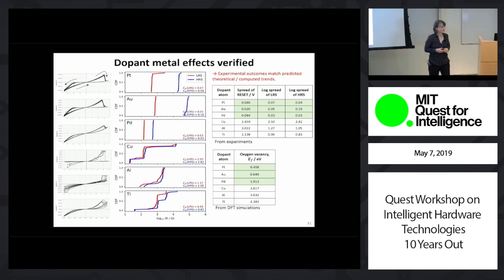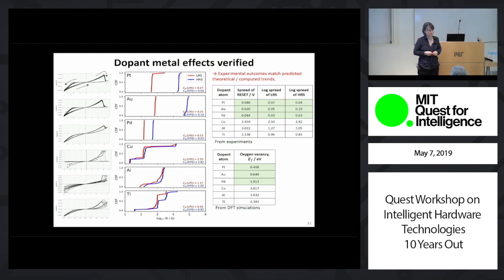Well, I'm wondering if it would be worth looking into a gallium implantation, because the ion beam or FIB is made of gallium. If that were the case, we should see it upon implantation without the metal layer. So what Zenji did earlier is to just FIB mill and then put the metal contact, and it doesn't work. So it's not the ion that we are milling with that is being implanted that gives rise to this effect. It's the metal itself that comes from the contact.